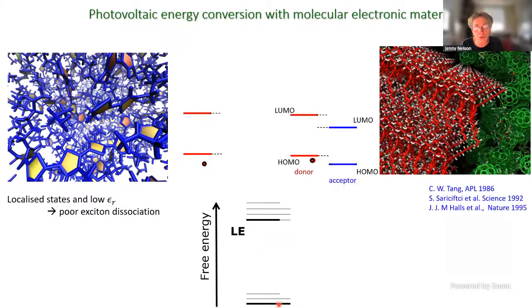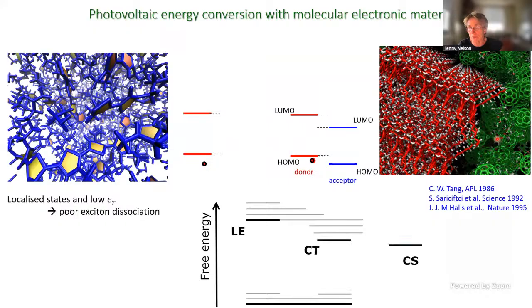So what we do to solve this problem is we introduce another material. So we then have two semiconductors, two organic semiconductors, and they would differ in their energetics. If we look at them as semiconductors, they form a kind of type 2 heterojunction, where in one material the electron will be stabilized, and in the other material the hole would be stabilized. And this has the effect of changing the distribution of states that are available.